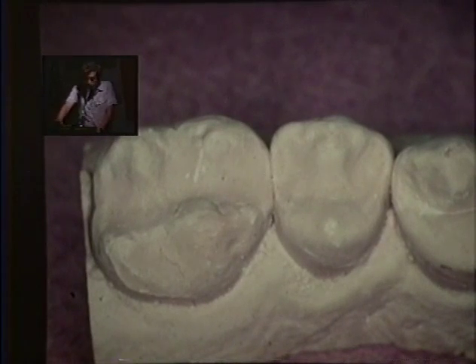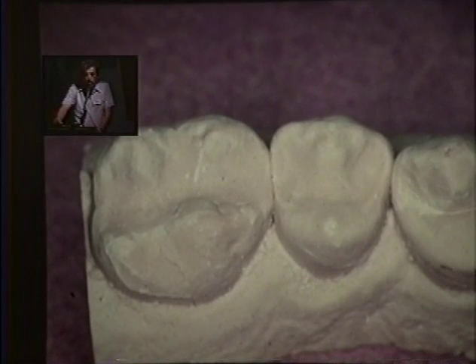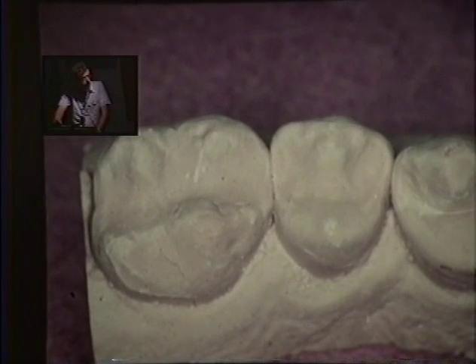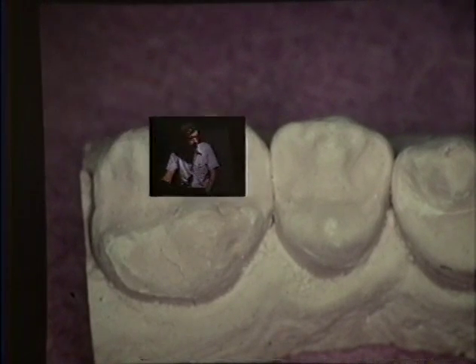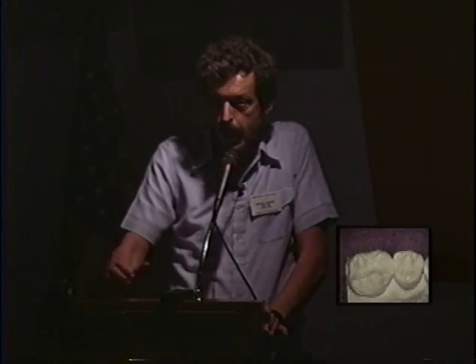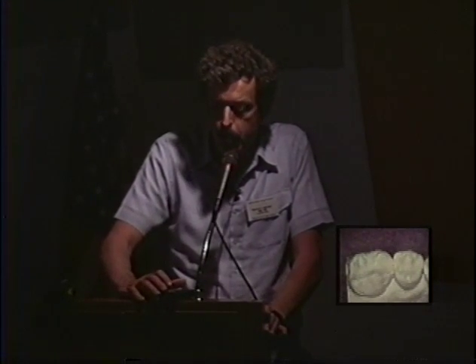Now that filling took about 1 or 1.5 minutes longer to place than the other one did, because what it involved was going back, re-etching the margins after the final grind in, re-etch the margin with phosphoric acid, wash it and dry it, and then put on a penetrating sealant, one that would penetrate down in there. Now, ideally you do this under rubber dam, but the problem is then you check the occlusion and you end up grinding a little bit. So ideally what we do is we seal the margins first, take the rubber dam off, grind in the occlusion, then seal the occlusal last, and then you have the best of both worlds.